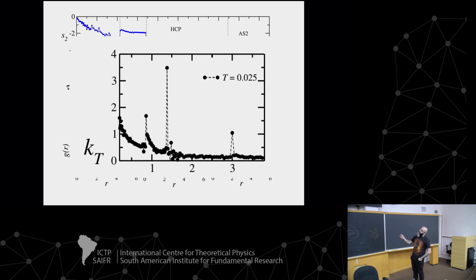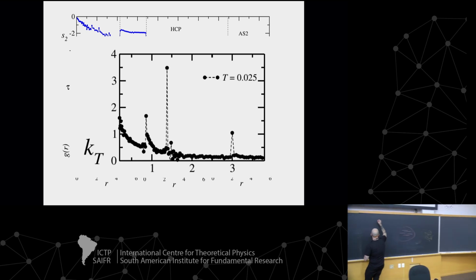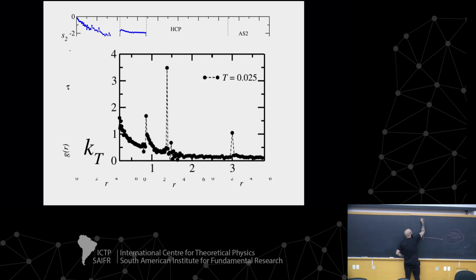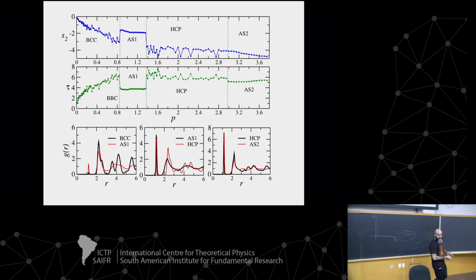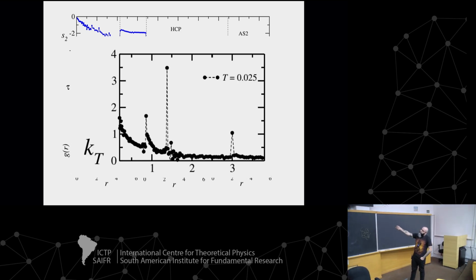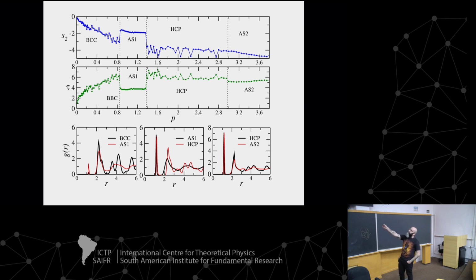And when we go back to the KT, here I'm fixing the temperature and increasing the pressure. So if I'm trying to build, remember, a kind of phase diagram, here is temperature, here is density or pressure. I can go by two ways. If I take, for instance, the specific heat, I do this kind of analysis, so I go up. If I take the KT, I fix my temperature and see what happens as I walk this way. Remember, thermodynamic path. And what we found was that all of these discontinuities are related to phase transitions from a solid, BCC, to an amorphous phase, then another solid, HCP, and another amorphous phase at higher pressures or higher densities.